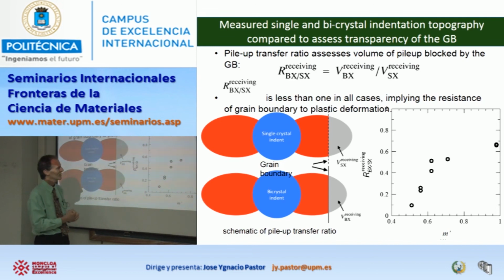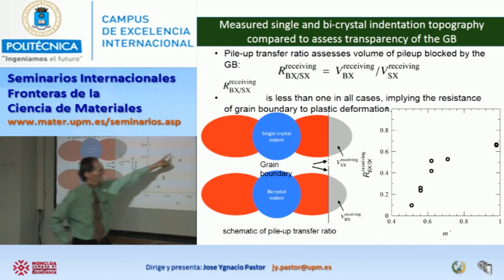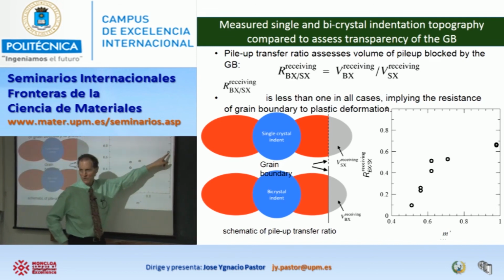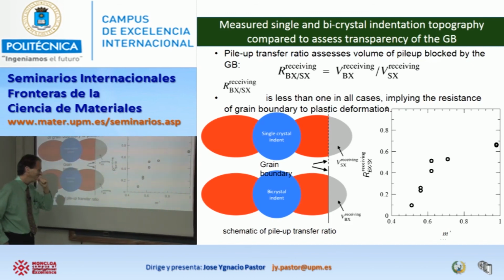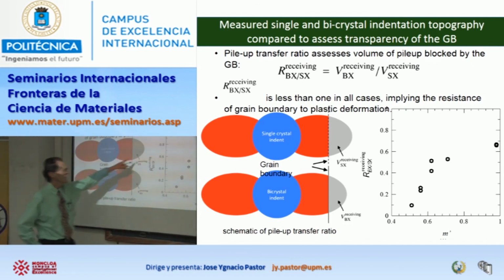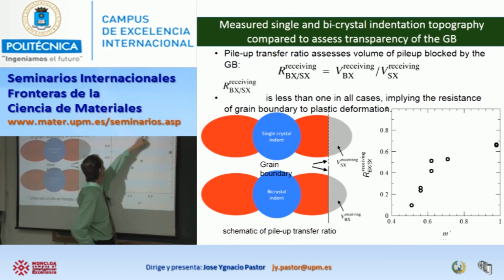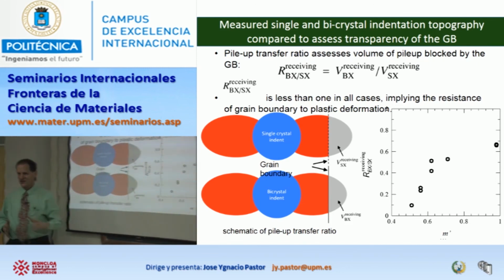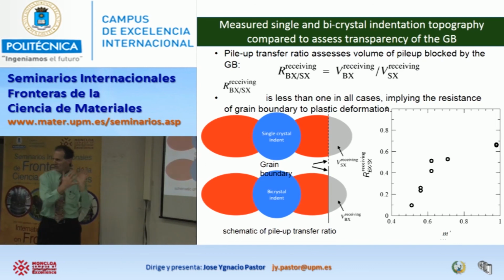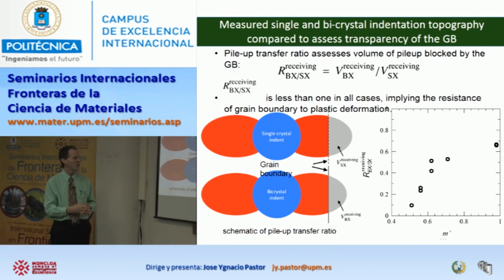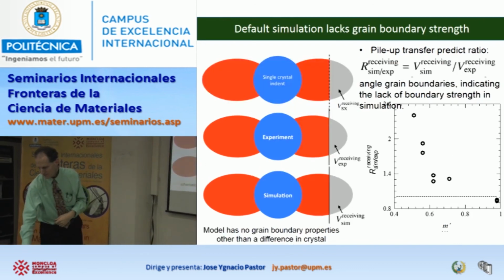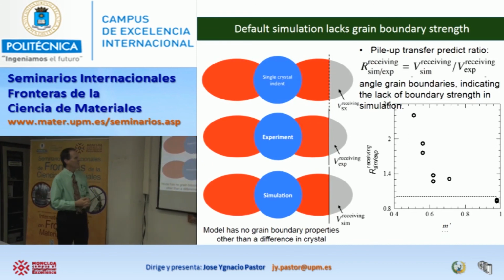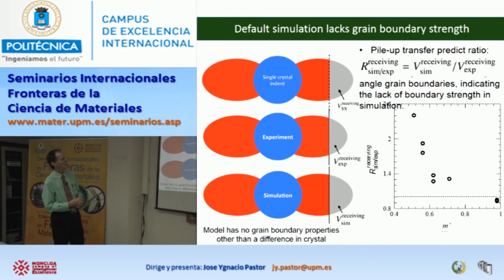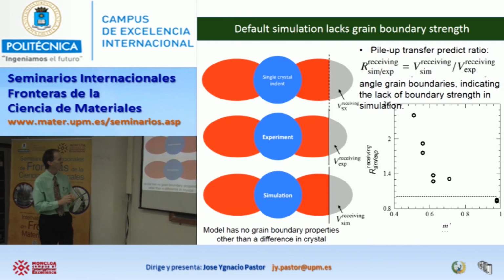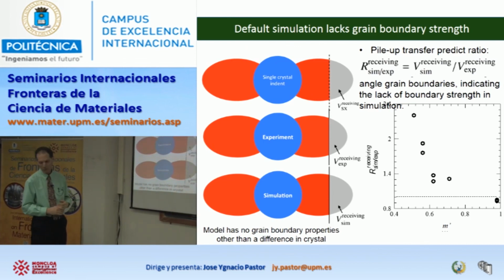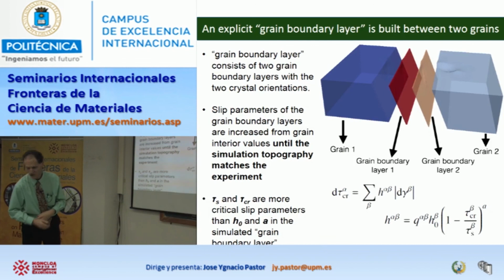blocking slip. Now, what's interesting is that even if I have nearly perfectly aligned boundary grains, I still have a resistance. It's not 1. That means even a low-angle grain boundary can create a resistance for slip to be transferred. And this is pretty much the same story that I just said, but looked at in a somewhat different way. But I think I don't need to go there.